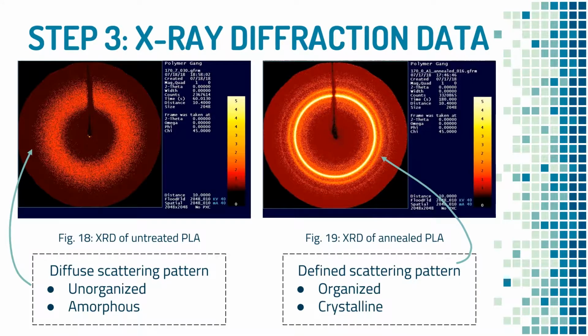can be represented as a point on this scattering graph. So this on the left here is a scattering graph of untreated PLA. And what we can see from this is it's a relatively diffuse scattering pattern, meaning that the structure of untreated PLA is relatively unorganized and amorphous. On the right, we can see more well-defined and intense rings, meaning that this is a more defined scattering pattern. From this, we can conclude that the structure of annealed PLA is more organized and more crystalline.